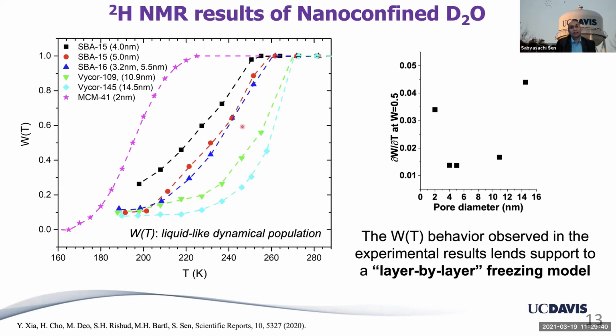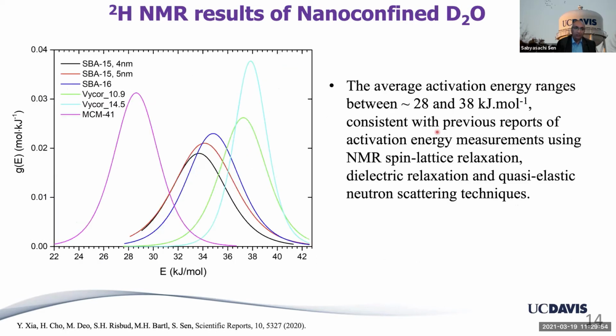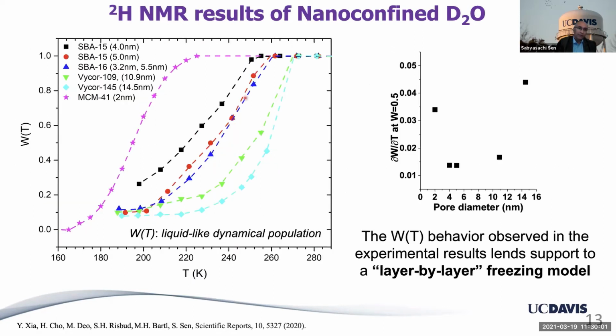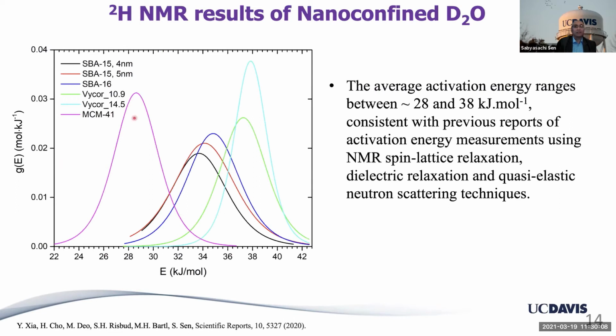And you can see this also very clearly if I take the slopes and plot them as a function of pore diameter, that it goes through a minimum here. The slopes are quite steep for the smallest and the largest pores. You can also derive from these transformation versus temperature curves a distribution of activation energies for these freezing processes, or the water mobility associated with the melting-freezing dynamics, and we get activation energies ranging between about 30 to 40 kilojoules per mole, which is in very good agreement with other studies on water using, say, dielectric or neutron scattering techniques. So that's all good.